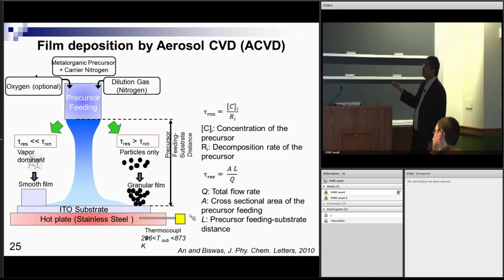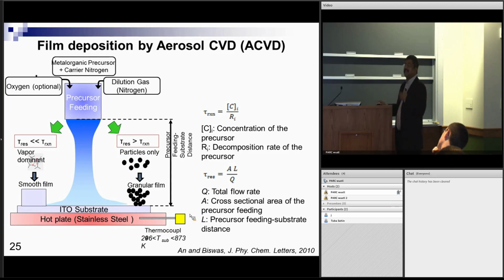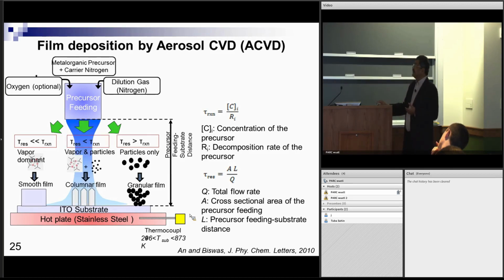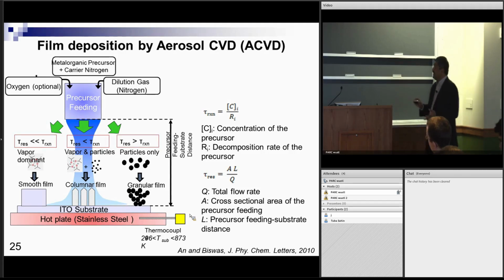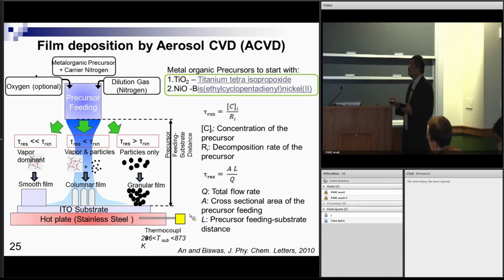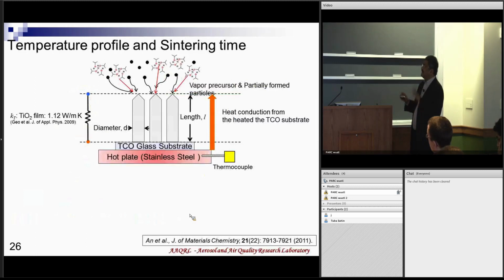Okay. On the other hand, if the residence time is much greater than the reaction time, I'm going to form particles, and if the particles grow to be large enough, I'm going to get a granular film, because large particles sinter at a rather slow rate. On the other hand, if I have the right intermediate conditions, I see that small particles deposit here and they sinter out, and then the single crystal structures grow, and I get this kind of a columnar structure. So this is an ACVD process and I can do it with different precursors and so forth.